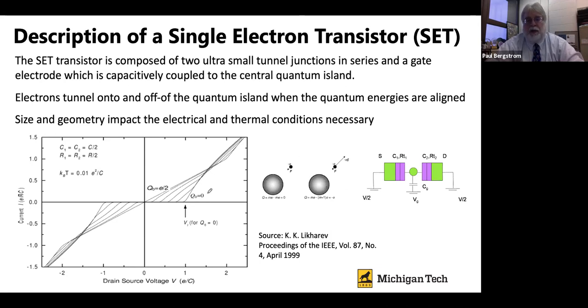And you'd have a gate in a similar fashion. But in this case, now we have a tunneling effect, which is a quantum mechanical behavior where an electron or a charge carrier can actually move, even if it doesn't have an excess of energy beyond the energy of the barrier. So it can actually tunnel through the barrier under the right conditions. And so this leads to some very unusual characteristics. It allows for a region where the device can have what's called a Coulomb blockade region, which can be changed based on the gate potential that's controlling the quantum dot, as well as something that's called Coulomb oscillations, which are fundamental charge transport that happens under certain current conditions.